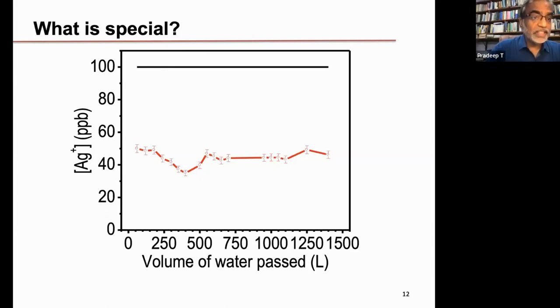But what is surprising is that with regular silver nanoparticles or anything that you put in solution, the silver ion release concentration will come down because water contains active ingredients such as silicates. The silicates sit on, in presence of calcium, you have a calcium silicate. This calcium silicate, even if it is 1 nanometer thin, the silver ion concentration comes down, this material is no more effective. However, in this particular porous structure, you can release silver ions from the pores, but nothing can go into the pores and block it.